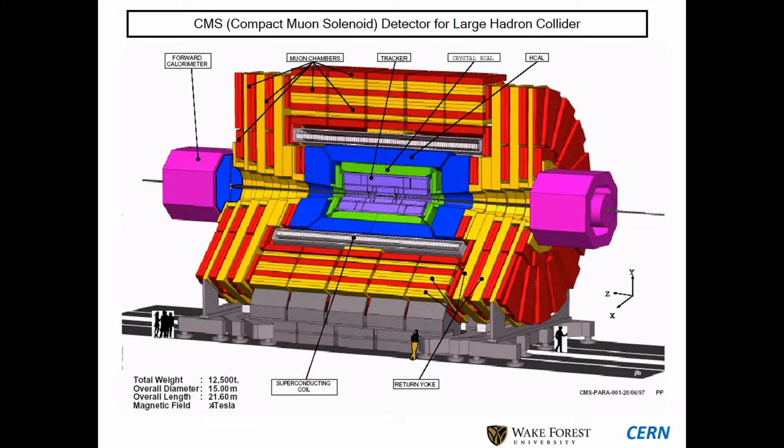That contains 68,000 individual crystals, single crystals about this long and about that big. And you probably could carve 4 of those crystals from one boule, but there's such a high selection going on to discard the defective ones and so forth. You sort of count, it's going to be 1 week of high temperature furnace time to produce every single crystal. So that's 68,000 furnace weeks to go.